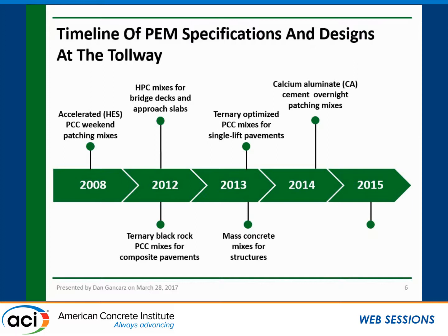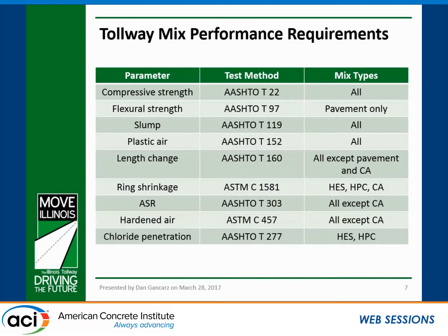In 2014, we developed a spec for calcium aluminate cement mixes, which is used for overnight patching, where we typically see 4,000 psi in 4 to 6 hours, depending on temperature and other factors. And then also on the eastern end of I-90, we implemented a performance-related construction specification for concrete pavement. So here's an overview of the Tollway mix performance requirements. All our mixes, we evaluate compressive strength. We look at flexural strength for pavements only, slump, plastic air, all mixes.